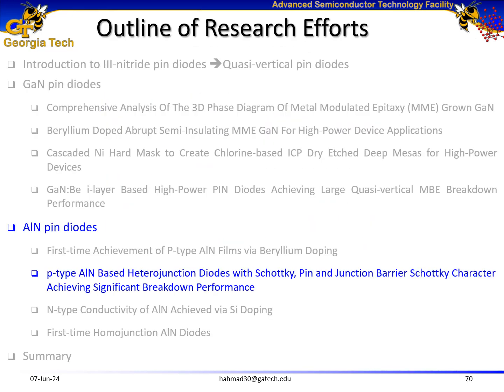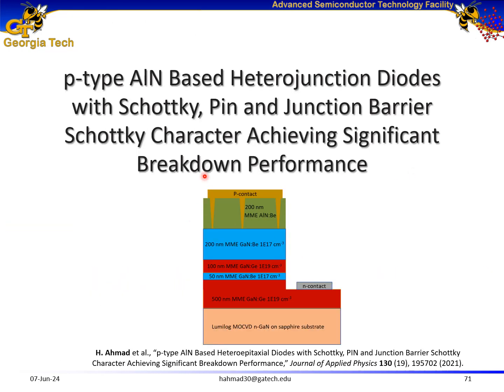Then we wanted to apply the p-type aluminum nitride to devices, but at that time, we did not have a source of n-type aluminum nitride inside our MBE chamber. So I performed a study on p-type aluminum nitride-based heterojunction diodes with Schottky, pin, and junction barrier Schottky character, achieving significant breakdown performance.